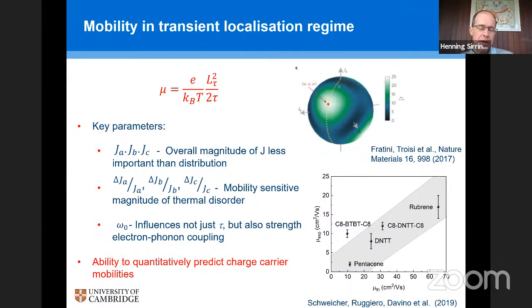One of the characteristics that's very important is how isotropic the transfer integrals are. The transfer integrals are calculated between pairs of molecules, and it depends, of course, in which direction of the unit cell you go. So there are typically three different transfer integrals, JA, JB, JC, corresponding to different directions in the unit cell. These are transfer integrals within the two-dimensional pi-stacked planes. As I said, the molecules have this layered structure. In the third direction, the transfer integrals are usually very small, and that's not what we're talking about here. We're talking about the transfer integrals in these herringbone-packed conjugated planes. And what you want is that the distribution of JA, JB, JC is as isotropic as possible. That gives you the highest carrier mobilities.